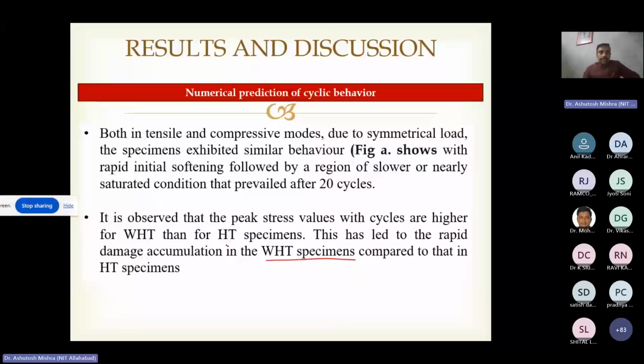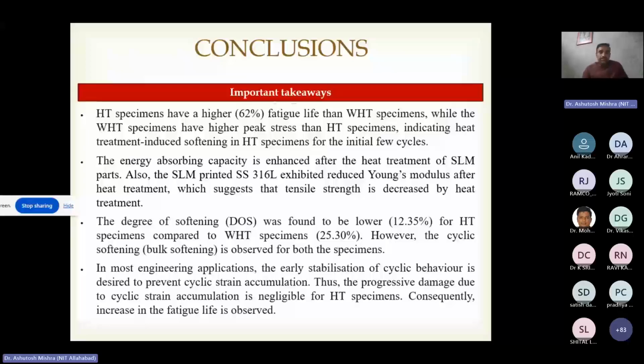Now, important takeaways. This is the last part and the conclusion. If we see the heat-treated specimens, the HT specimen has exhibited 62% higher fatigue life compared to the WHT specimen, while the WHT specimens have higher peak stress than the HT specimen, indicating heat treatment induced softening in the HT specimen for the initial few cycles.